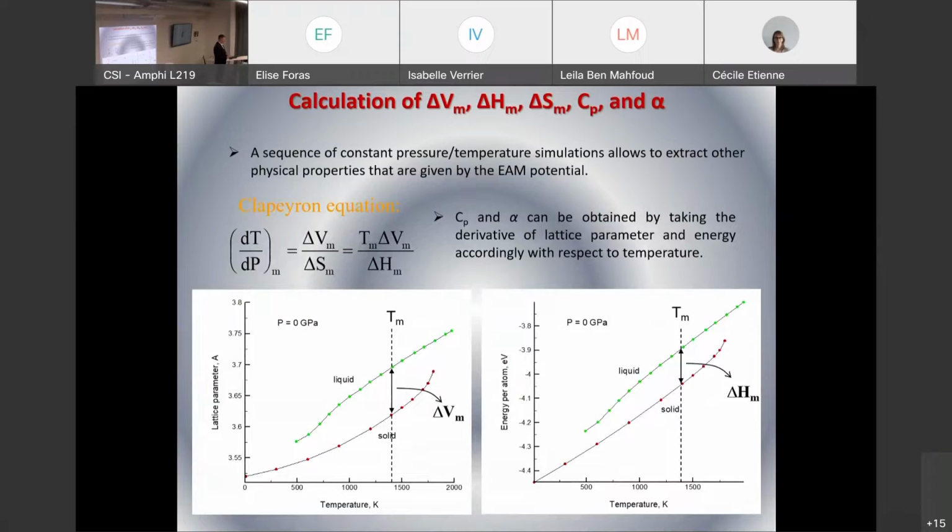In particular, at a certain temperature, we can choose such a lattice parameter that the established pressure after equilibration at this temperature will be zero, so normal conditions. Of course, with the heating of the crystal, the material will respond by thermal expansion, and the lattice parameter will increase. From exactly the same modeling, we can also plot the points which correspond to the energy per atom at this temperature.